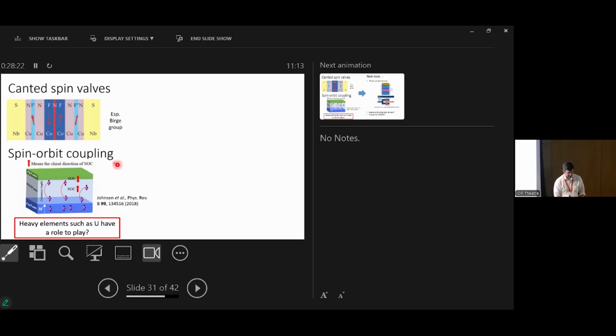And more recently, so in the last few years, people have become increasingly interested in using spin-orbit coupling, again, as we heard in the last talk, to mix the spins up. So instead of this simple spin singlet, you have all the possible combinations. And we filter out then the triplet component, which can penetrate into the ferromagnet. So many people in the literature have used a heavy element like platinum or palladium or gold. Of course, I'm interested in using uranium, which is as heavy as it gets.